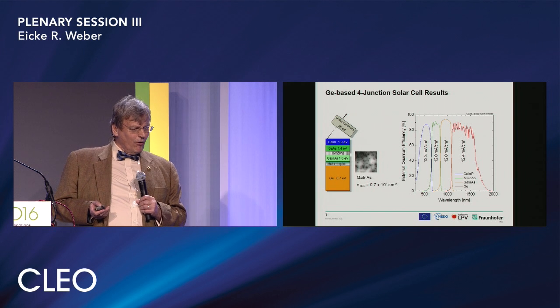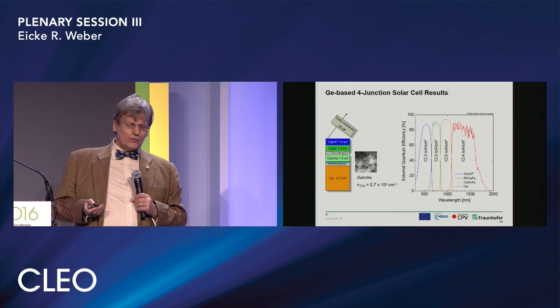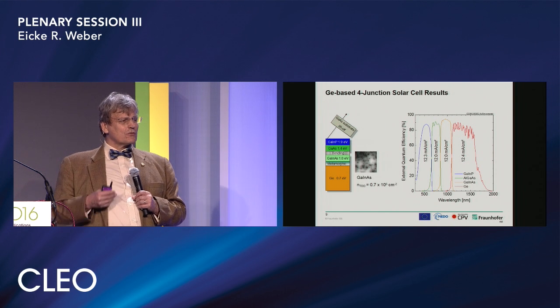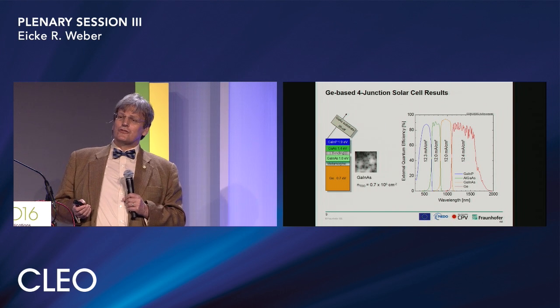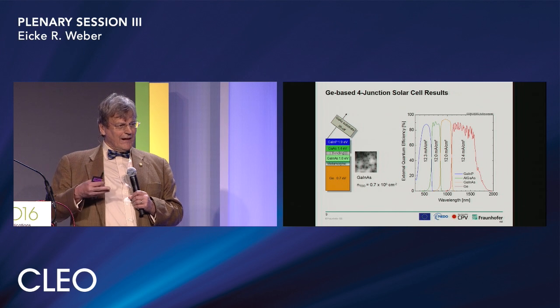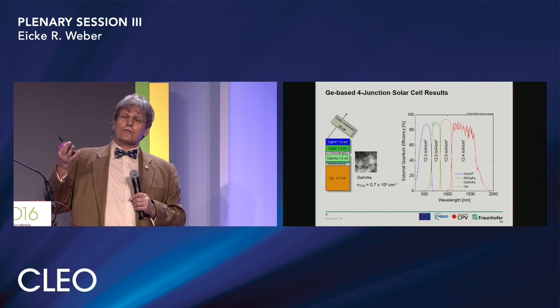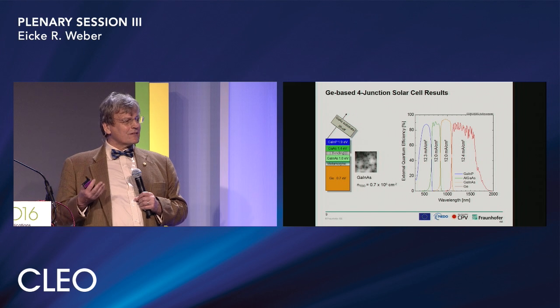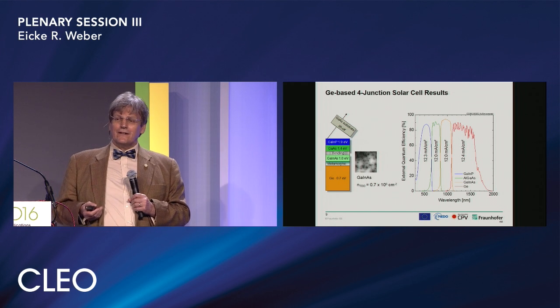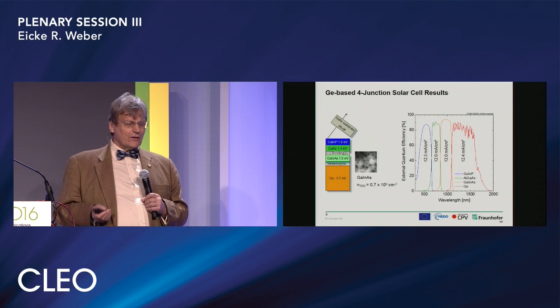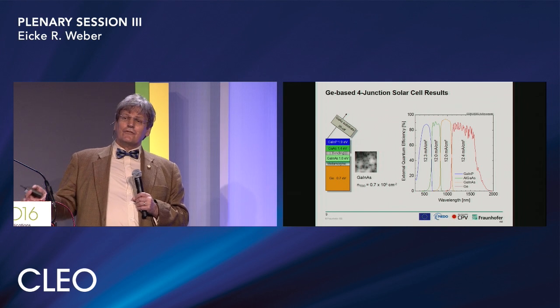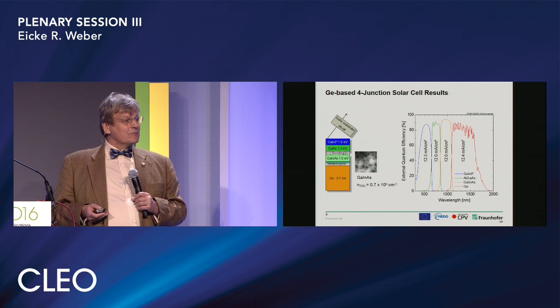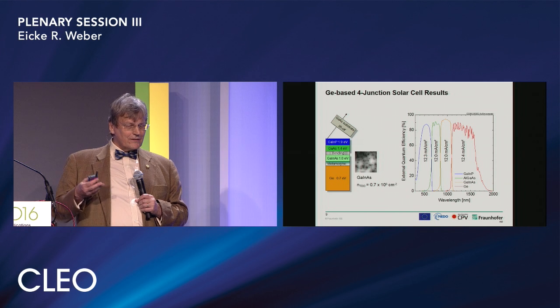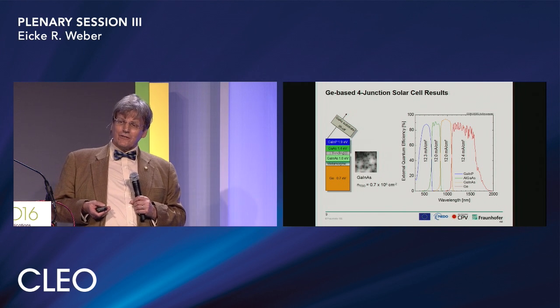What is very important in such a structure is a so-called current matching, because whereas the voltages which you create from each of the layers when you shine light on the structure simply add up, the current has to go through the whole structure. And this means it makes no sense that in one layer you could create 13 or 14 milliamps per square centimeter. If in another layer you get only 9 milliamps per square centimeter, the weakest link determines the current. And you see, one can do a very good job in current matching.